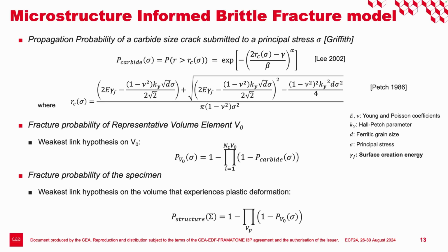So the key element of this modeling is to consider first that a crack initiates from carbides as soon as we have plastic deformation of the matrix. And once this happens, the initial size of the crack is equal to the size of the carbide from which it has initiated. So once you have a crack, the probability for this crack to propagate is given by a Griffith criterion. So the probability for a crack to propagate is the probability to find a crack larger than a critical size. This is given by the Weibull distribution I have shown you before, when we were studying by image analysis all the carbide sizes.